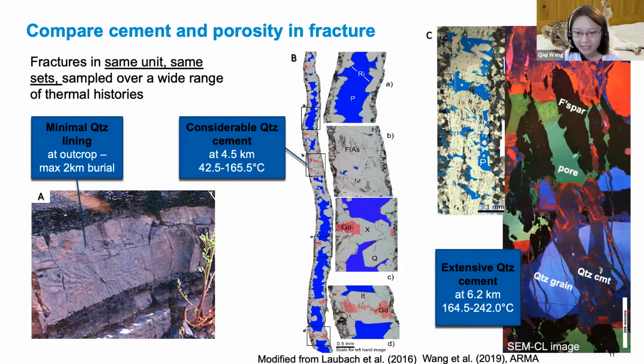And I also want you to pay attention to the quartz cement crystals growing into the pore space near the feldspar, those ones. So you see the faceted crystal faces. They mean the quartz crystals reached their euhedral state. They had enough time and enough space to grow, but the cement was just never enough to fill out the pore space associated with the feldspars. So this is another strong evidence saying that the feldspars, and in some cases lithics in the rock, help retain the fracture porosity.